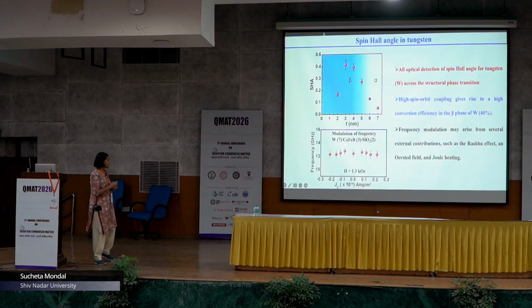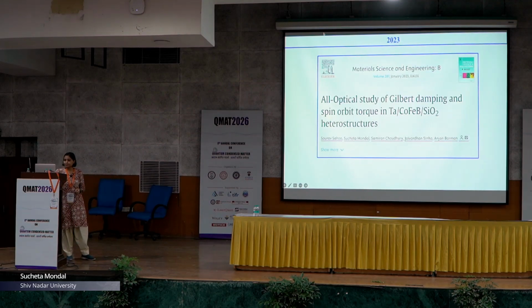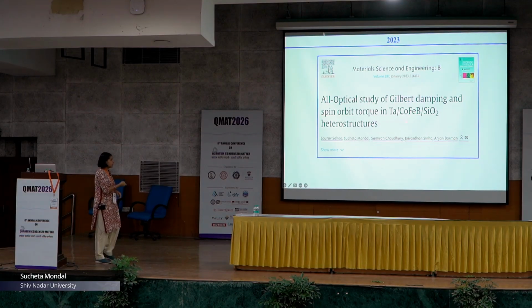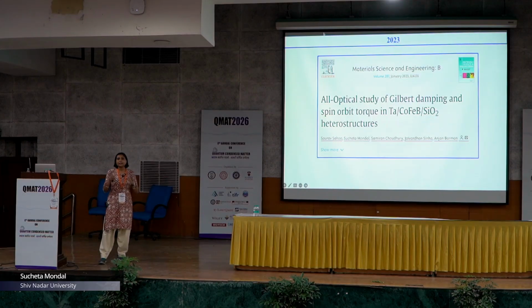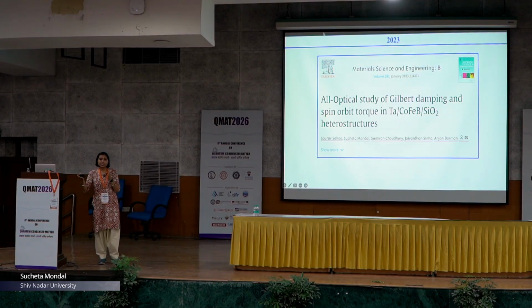We have also shown the change in frequency, but this frequency modulation is symmetric on both sides with the charge current polarity. This indicates slight Joule heating or heating effect in the devices. Later in the talk I will just briefly touch on this: using a beta tantalum cobalt iron boron system, we also segregated the amount of real change from charge current and the effect of heating, and how we can segregate them.